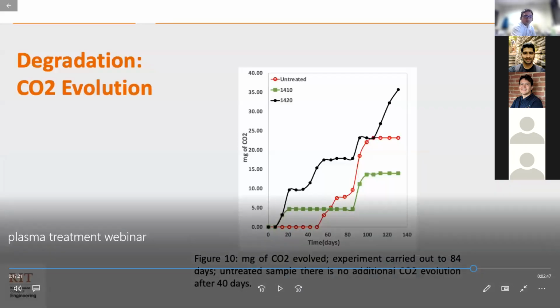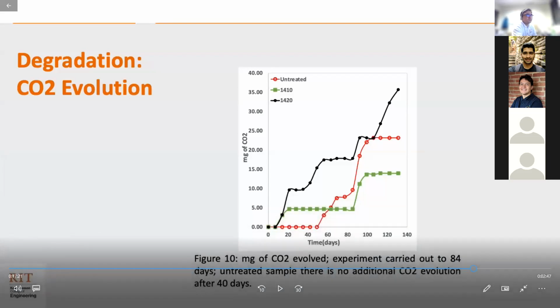So, yeah, that's a good question. The way that we view this is that the degradation is primarily occurring at the surface level as opposed to occurring throughout the bulk. It wasn't presented here, but through the course of our degradation experiments, we've also measured things like the molecular weight of the polymer. And we found that the molecular weight of the polymer doesn't appreciably change in spite of the fact that we see this evolution of CO2 and the degradation as observed by the SEM images that he showed. That leads us to conclude that it's primarily a surface phenomenon, sort of like peeling the layers back of an onion. We're degrading the surface, it's degrading away, and then continuing to do so as it progresses through the bulk. Okay, awesome. That's exciting.